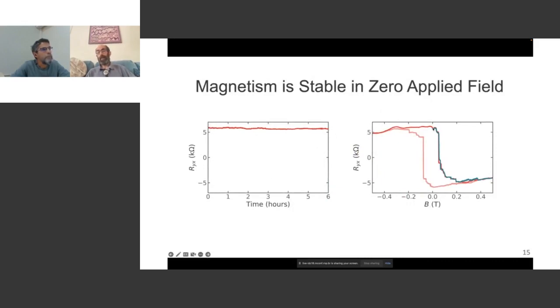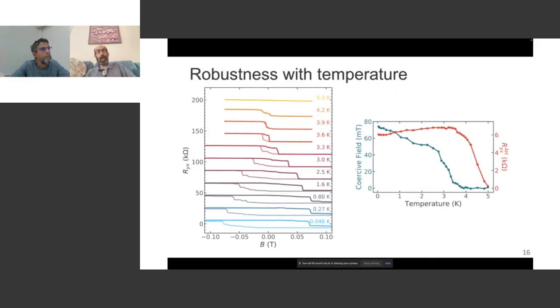So we did a hysteresis loop in field, came back to zero field, waited for 6 hours, the Hall signal barely changed, and then we continued on, and it was as if we had never waited. So this is a stable magnet, albeit at low temperature. How low a temperature? It turns out the magnet remains magnetic up to about 4 Kelvin or 5 Kelvin, depending on what measure you use for it. And this is about the temperature at which liquid helium boils. So very low, but not an extreme condition for condensed matter physics.